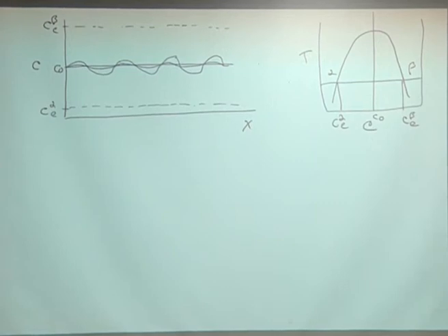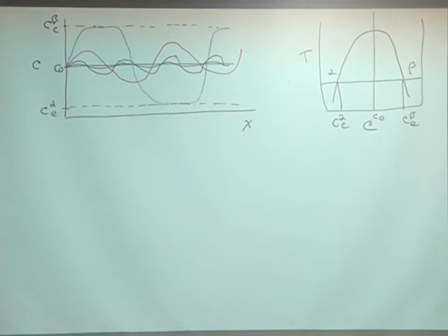The equation becomes nonlinear, and so you begin to get shifts in the wavelength as the amplitude gets bigger, and as time goes on, eventually you end up with compositions that approach the equilibrium compositions C beta E and C alpha E. Okay? So that's a sketch. I'll show you some pictures of how this evolves in a second, and in fact, you'll be able to produce much more realistic ones this afternoon.